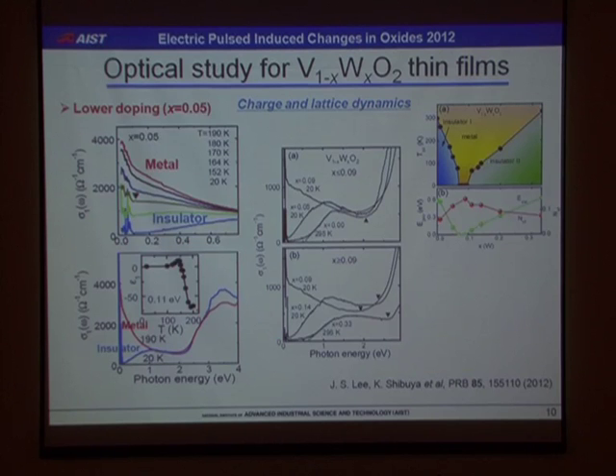And we also investigated the charge and lattice dynamics by optics for these thin films. Here is the optical conductivity for x equals 0.05, and it is monotonically reduced with decreasing temperature. We can see the spectral weight change from this region to the higher energy region, indicating the role of electron correlation. And here we have a composition dependence. The gap of non-doped VO2 collapsed in the metallic region, and a Drude response was obtained. With further increase of concentration, the gap opens again. This is consistent with transport data.